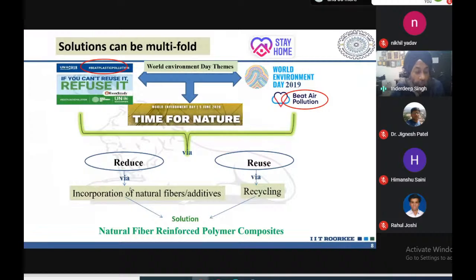We are not going to compromise on the functional requirements, aesthetic requirements, or other special requirements of that product. The only thing is, from the material selection point of view, instead of using 1 kg of polymer, we are going to use 700 grams of polymer and 300 grams of natural fiber. So that will lead to the reduction. That is the theme you see: if you can't reuse it, then refuse it. We cannot directly refuse, but slowly we can try to tailor our product with those materials which can be environment friendly.